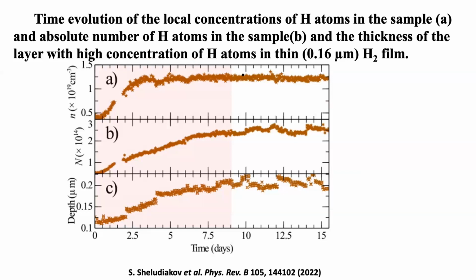I don't know if you believe it or not, but this is the dependence of the local concentration, as usual, it is saturated. And this is total concentration. It comes to here, and after that, we think that it's stabilized in penetration depth. This peak is the influence of transferring helium in our Dewar on the amplifier of the spectrometer, but you see that after relaxing, it goes to this level.